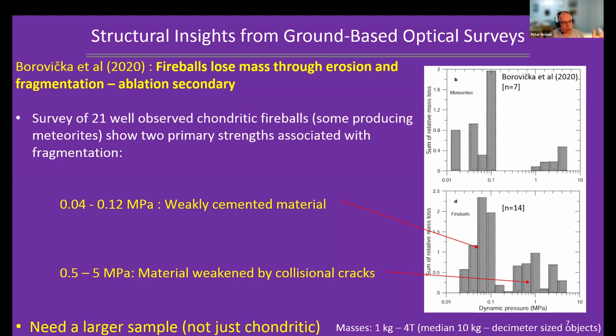And to first order, you'd think, okay, these objects are coming in, they have cracks that are probably related by some sort of Weibull distribution. So you should see sort of fragmentation as a continuum through pressure. And that's not what they see. It appears that at least for ordinary chondritic-like fireballs, there are sort of two stages to fragmentation. There's a lot of material that's released under a tenth or less of a megapascal, so at very high altitudes under very little pressure, and then a quiescent phase at a few tenths of a megapascal, and then again at a few megapascals, a lot more material is released.